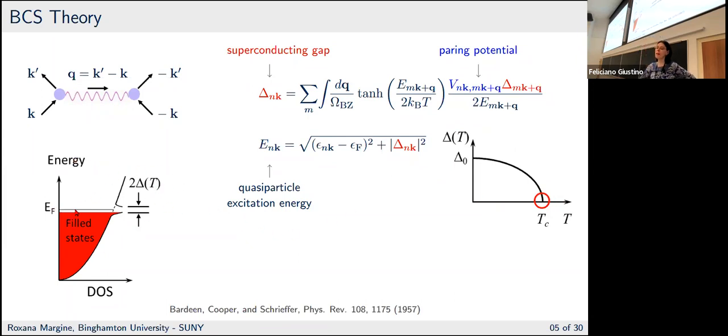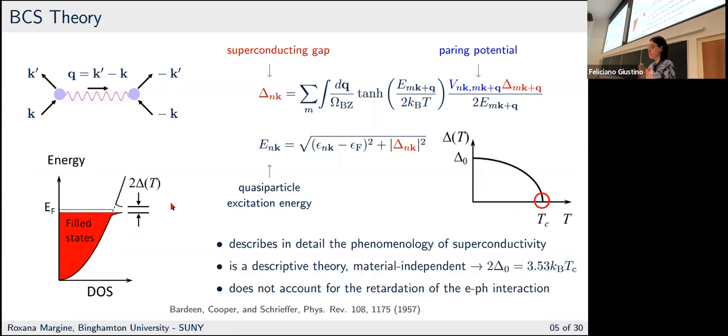And the reason why this gap forms is that these Cooper pairs now don't behave like fermions; they behave like bosons. So it means that you can have more than two electrons in the same state. As a result of this, you'll have this change in the density of states here, where you see this peak, which means that the electrons that initially occupied this area are now accumulating at the edge of this gap.